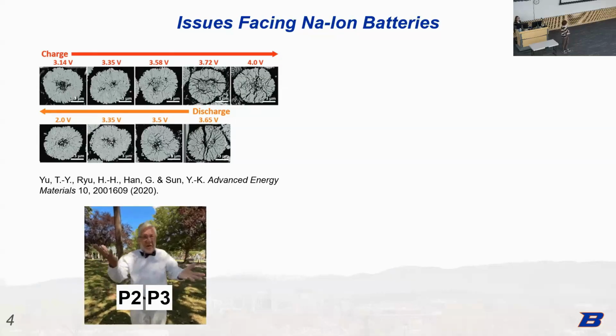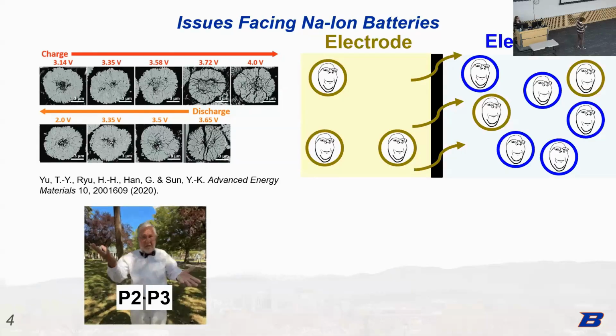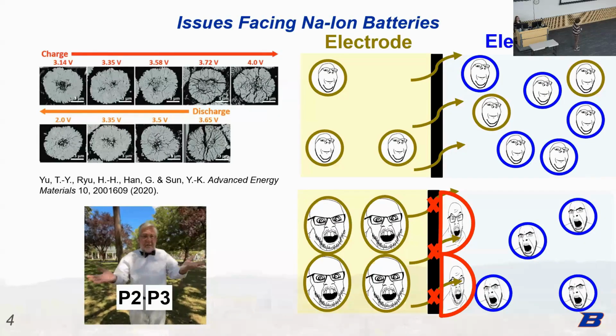The last problem I want to talk about is that when sodium-ion batteries are actually functioning, at the very beginning of them, at the interface, you can see the sodium ions are very happy. Well, the electrolytes are also very happy because this interface, which is the surface between the electrode and the electrolyte, is clean. The sodium ions can leave very easily. However, during multiple cycles, you form something that's similar to a film on that interface that then blocks these sodium ions from being able to leave. And as you can see, they are all very upset. So trying to figure out how to avoid the formation of this is very important.